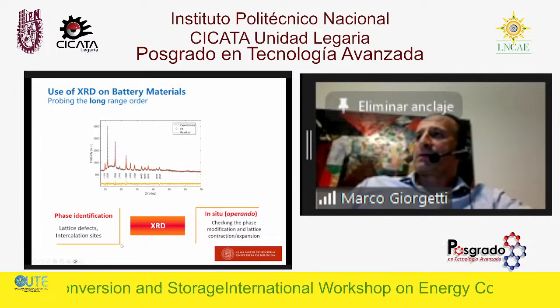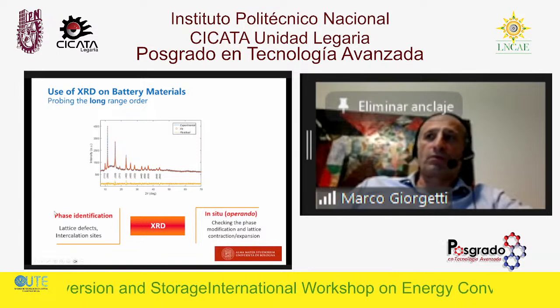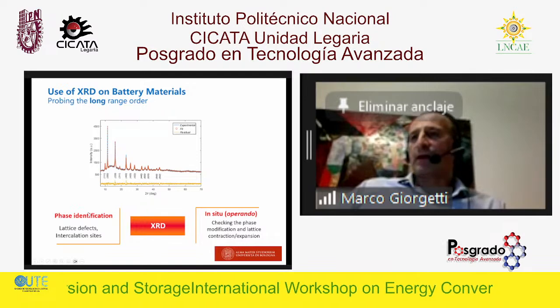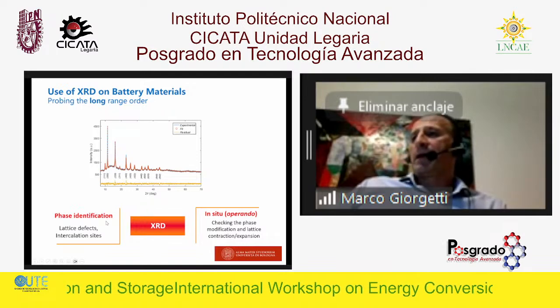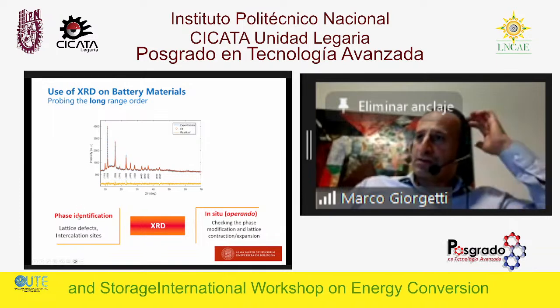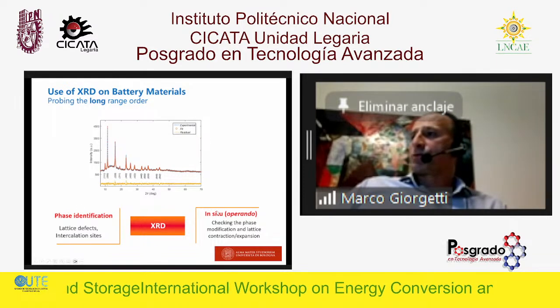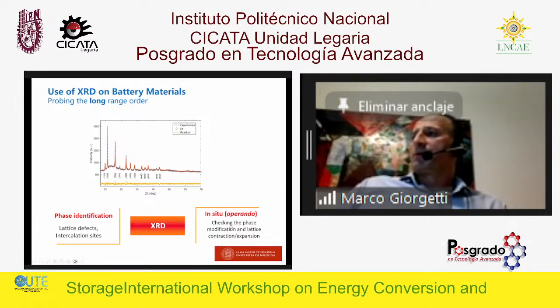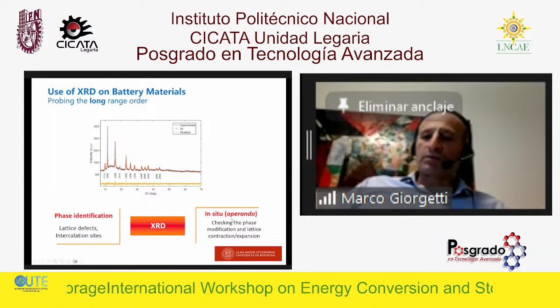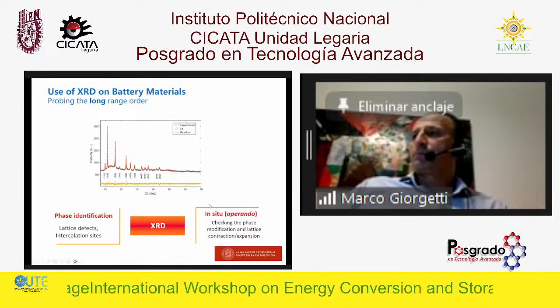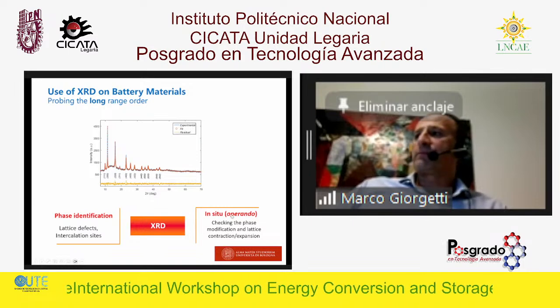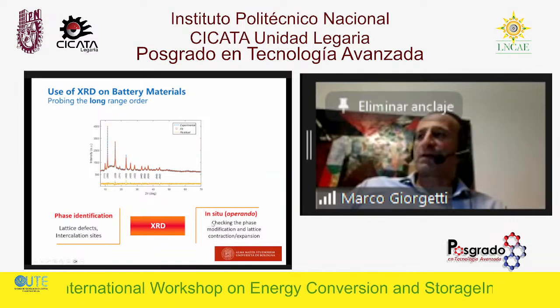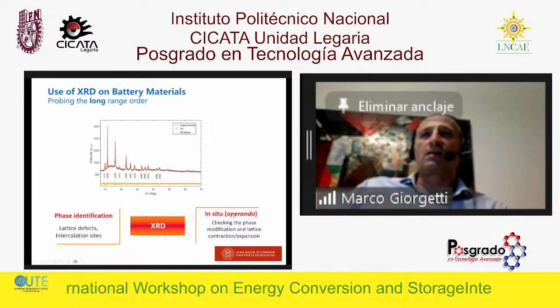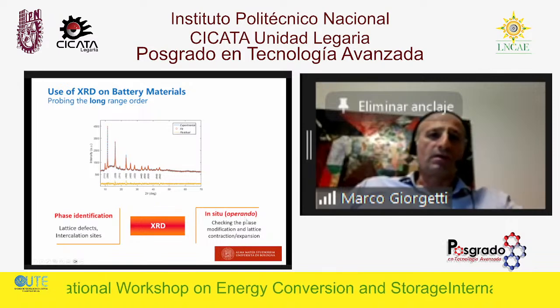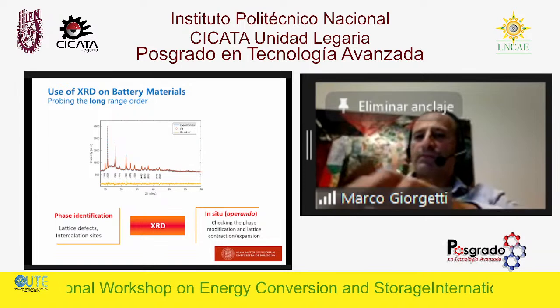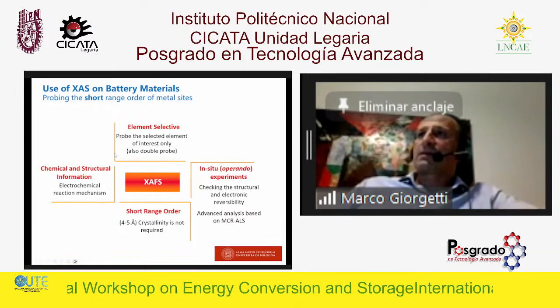In battery operation, it is very interesting because we can do phase identification, and see how much the phase is modified under operando conditions, for instance. And if you have very good crystallinity, we can also look at lattice defects and intercalation sites, and it opens up in situ operando experiments. I will not talk about operando experiments that can be done in a lab. I will just provide a few examples of the use of XRD using synchrotron radiation, but try to highlight the benefits of using these techniques at a synchrotron, even though, of course, it is widely available in the lab.